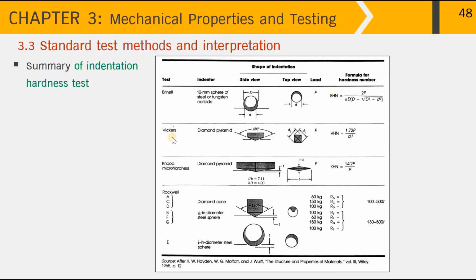That gives the Brinell hardness number. And for the Vickers hardness test, we apply the diamond pyramid with the square base of 136 degree included angle to produce the indentation on the metal surface of the square base here. By measuring two diagonals normal to each other, we can now calculate the VHN or Vickers hardness number by putting in the load measured and the average value of diagonals over here. And for the Knoop micro hardness, we apply the diamond pyramid with a narrow dimension over here onto the metal surface by using a small level of load. And to calculate the Knoop hardness number, we put in the load and the L dimension here. The first three give the hardness number based on load divided by the area.